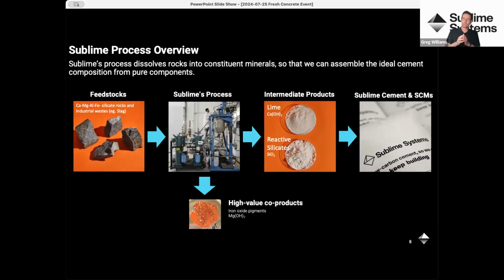These feedstocks are digested essentially by the Sublime process, and then we sequentially pull out the individual components of the mineral feedstock. Any elements that are not useful in cement chemistry, such as iron or magnesium, are removed. They're also purified as part of that process. They can actually be turned into other co-products for other industries. For example, iron oxide pigments for building materials, or magnesium hydroxide can be used in wastewater treatments and other chemical applications. But the two main ingredients produced are a hydrated lime, calcium hydroxide, and a reactive silicate. These are produced as free-flowing powders. They're then blended together with a few other additives, and that produces Sublime Cement.